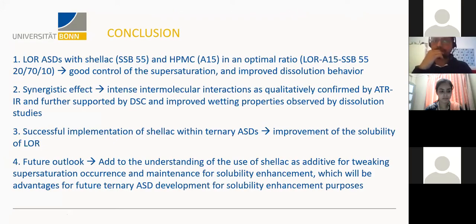To conclude, for loratadine ASDs with shellac and HPMC, the optimal ratio we found was 20-70-10, which showed good control of supersaturation and improved dissolution behavior. This synergistic effect was due to intense intermolecular interaction, which was qualitatively confirmed by ATR-IR and supported by our DSC results. We think this is due to the increased miscibility and improved wettability, which led to the observed dissolution results. Thus, with the successful implementation of shellac in the ternary ASD, we can achieve solubility improvement